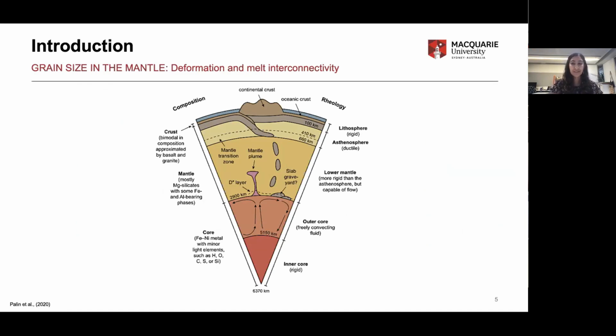And again, I'm using these qualitative terms because we have a really poor understanding of what large means. And we speculate that this could be meter-sized grains or centimeter-sized grains. We have no idea. The lower part of the mantle deforms in a diffusion creep regime, which suggests that grain size is probably small, on the orders of microns to centimeters. But again, these are orders of magnitude. And these are really important if we want to try and understand how our planet has evolved, how it's cooling, and where we will be in a couple of million years.